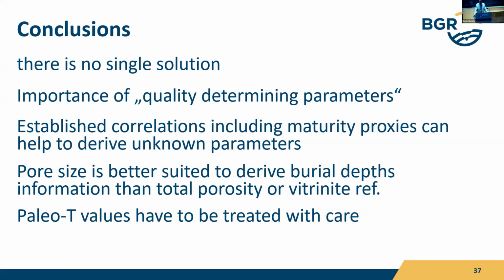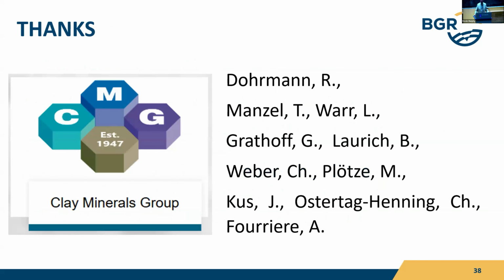Vitrinite is measured very often. But if you have a site where you're not sure, then it makes sense to measure the pore size as well, to have an idea if vitrinite reflectance really is providing sound results or not. Okay, and yes, that's what I also said, the paleo-temperature values have to be treated with care, but they're important anyway.